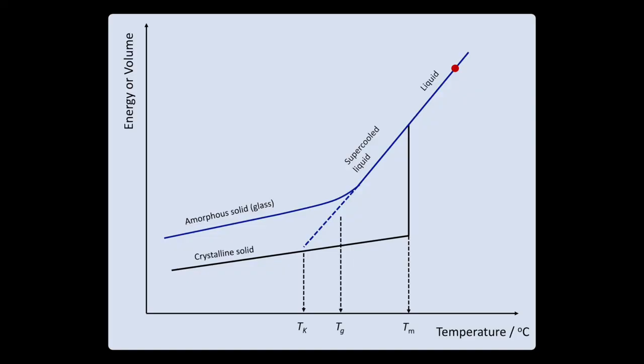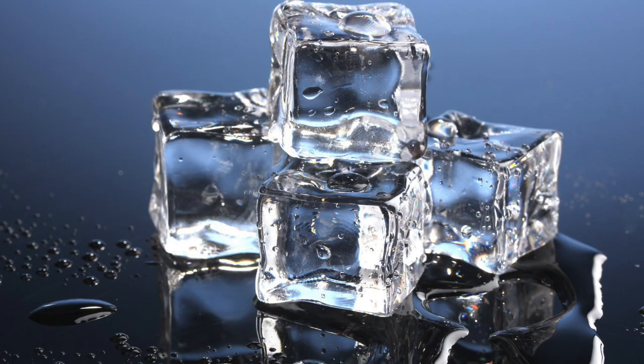At some point, the viscosity will become so high the material looks and feels like a solid. Effectively, the molecules have become frozen — although I prefer the word trapped. Frozen for most people means below zero, because they're thinking about water, but the principle applies to any glass at any temperature. The molecules are locked in position, and we say the material has formed a glass. A glass then has the structure of a liquid, but the viscosity of a solid.